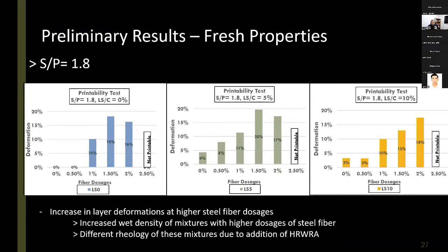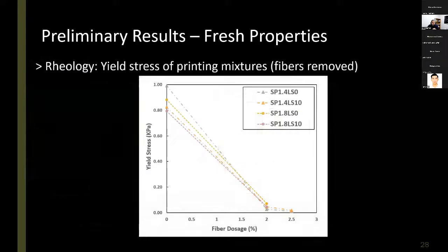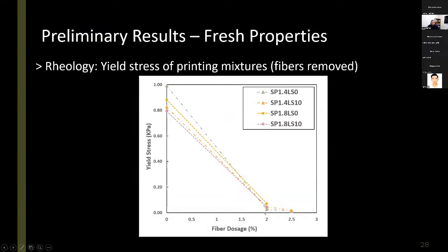And the other one is the different rheology of these mixtures. I told you we had a target workability range. And to reach that level of workability for our mixtures with fiber, we had to add more superplasticizer. And actually, when we did the rheological testing, we saw a very good correlation with the yield stress, which is the parameter we expect to be somehow related to shape stability.